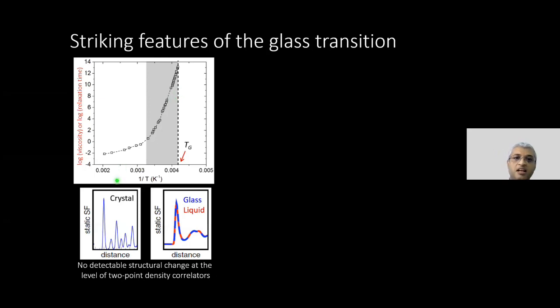And what is even more spectacular is that all the way from the liquid to the glassy state, if I were to look at the pair correlation function or the static structure factor, something that I can measure in an X-ray device, I see no perceptible change, at least at the level of a 2-point correlator. Not like the crystal transition where I see clear order develop as I go past melting. So that is to do with static structure.